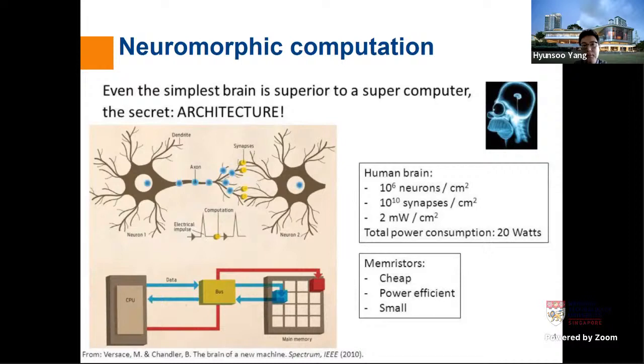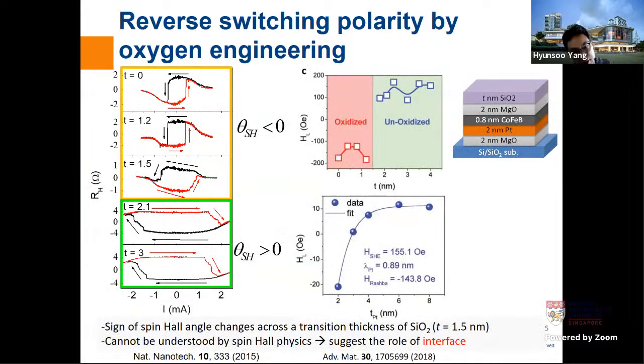So our history begins from the oxygen engineering in the spin-orbit torque devices. Initially in 2015, we found, depending on the amount of oxidation in our device, we can change the spin-orbit torque sign. For example, in a very conventional platinum cobalt iron boron bilayer, we typically cap with very thin MgO and silicon oxide on top. And depending on the silicon oxide thickness, once we cap with silicon oxide of more than 2 nanometers, then we find typically a positive spin Hall angle coming from platinum, as is well known. That is shown in this switching sequence here.